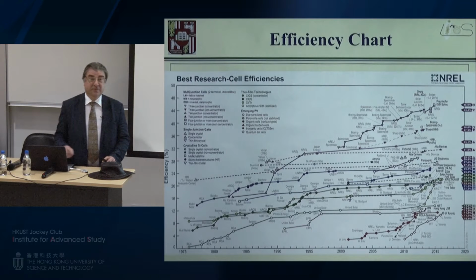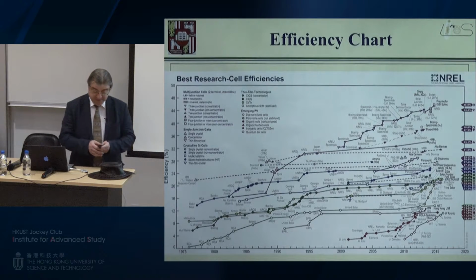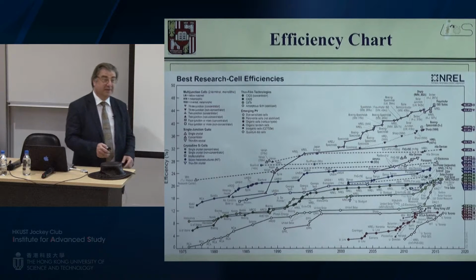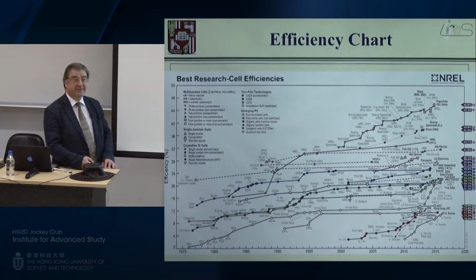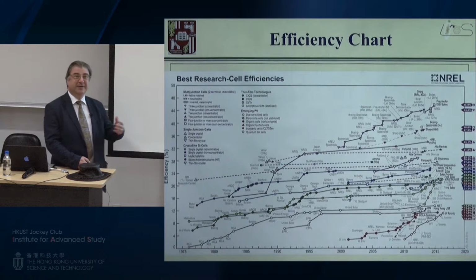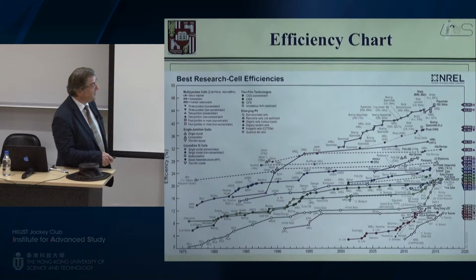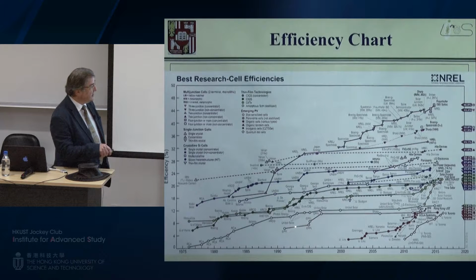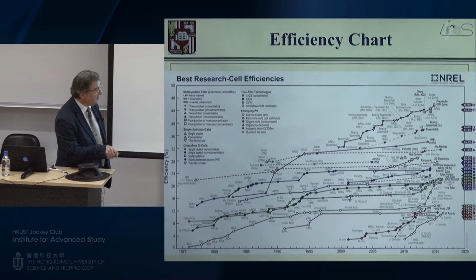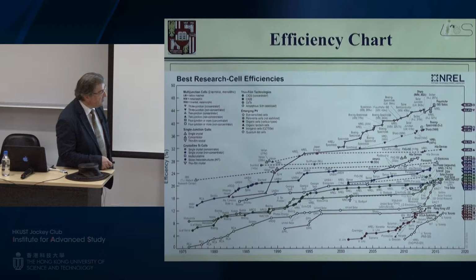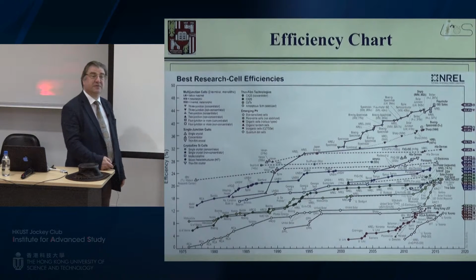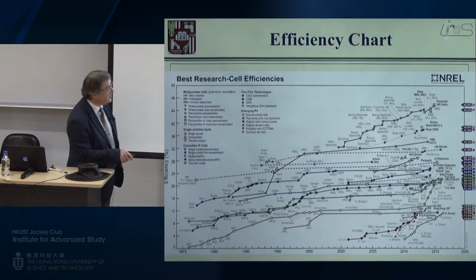Every solar cell lecture, of course, should present this famous slide of NREL, which shall be updated every week, because indeed the perovskites are getting weekly records reported somehow. And you can see, this is basically Michael Grätzel's work in the electrochemical dye-sensitized solar cells. This is our work with the organics. This is now getting really good, actually, also with Ted Sargent, and so these nanoparticles, I will come to this.